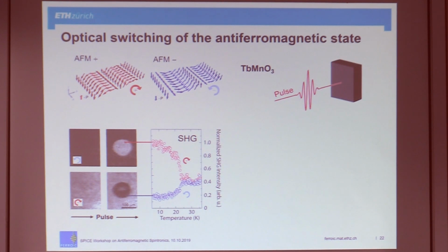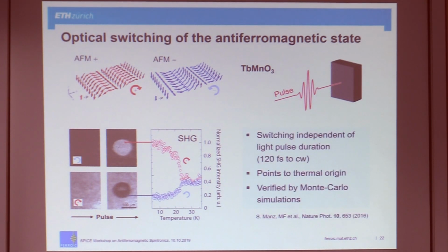At first, we thought this is super fancy and something with terahertz generation that we do somehow in our crystal and that manipulates the magnetic order. But it's much more mundane. So we did the same experiment with a CW laser. We used 120 femtoseconds, then we did it with nanoseconds, and finally with a CW laser, a continuous laser beam. So it's not related to any high electric field component of our light pulse. It simply is the energy of the laser beam. So we heat up our sample. That is not a bad thing. You can still do nice stuff with that.